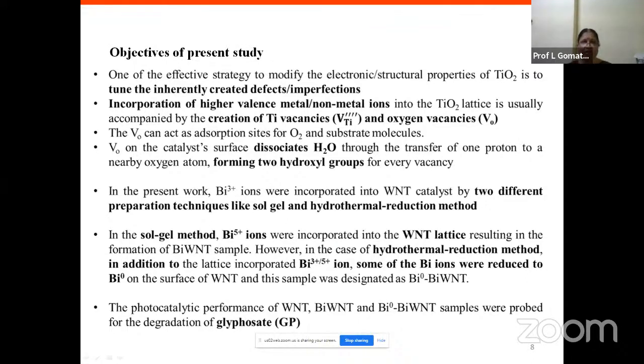In the case of the sol-gel method, Bi5+ ions were incorporated into the WNT lattice, whereas in the case of the hydrothermal reduction method, both Bi3+ and Bi5+ oxidation states were present. In addition to these ions, some of the bismuth ions were reduced to the Bi0 metallic state and deposited on the surface of the WNT catalyst. In this research work, the pollutant we have taken is glyphosate, which is represented as GP.